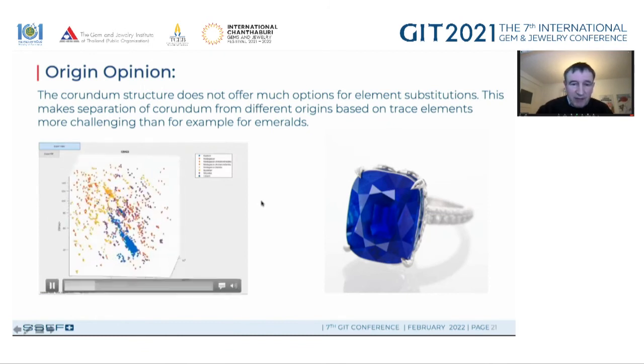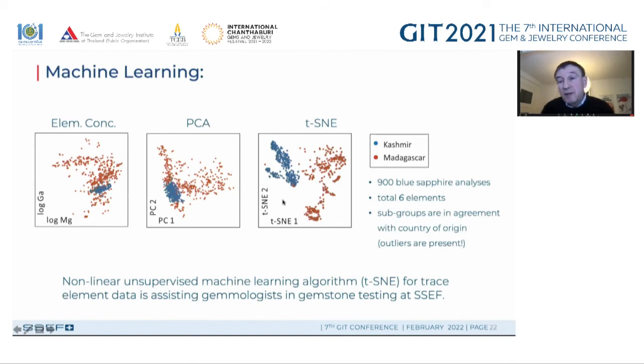So we have to try to use statistical methods. And by using statistical methods, what we try is to have a clear pattern to be able to make separations. So starting from just two elements, scatter plots, gallium versus magnesium, and we have only Kashmir and Madagascar sapphires chosen, we can start in a first attempt with a linear statistical approach, PCA analysis, still a large overlapping, or, and that's what we have gone into, nonlinear, unsupervised machine learning algorithm. So we use machine learning to get a better answer on origins.